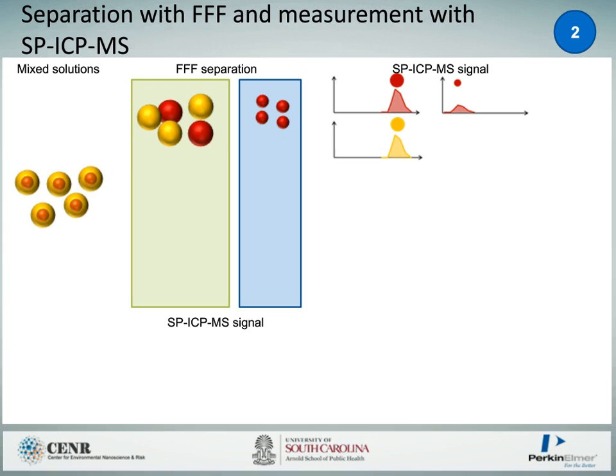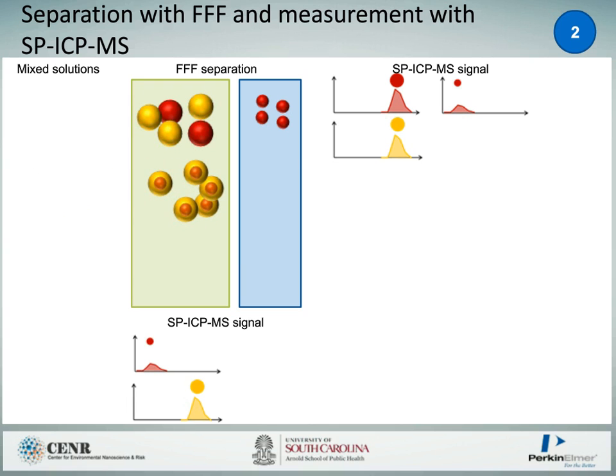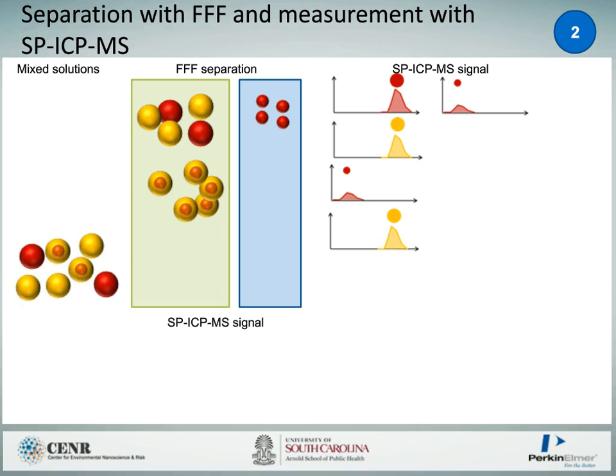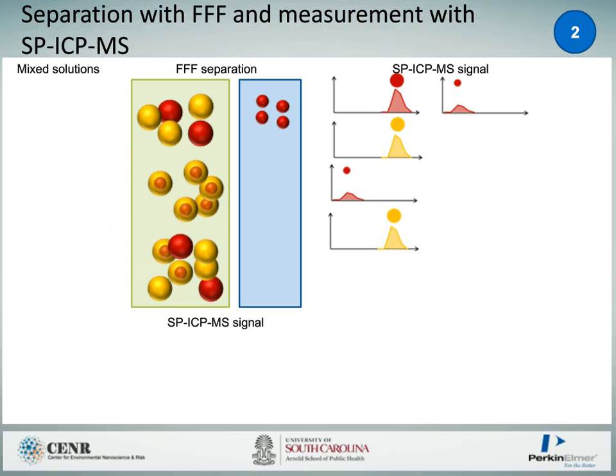So then if we looked at a bimetallic particle, say a core shell material, of a larger size, when those elute, they're only going to come out in the later fraction. But then when we measure with single-particle ICP-MS, we're going to see a much smaller size for the core and a large size for the shell. This is to do with the x cubed number of atoms per nanometer of particle as you go out in diameter. So then if we had a mixture of monometallic and bimetallic particles, these will all elute in the later fraction. And at this point, what we're going to end up with is two peaks coming in the gold signal, where we're having a small fraction from the core shell material and a large fraction from the monometallic material, and then we're going to see the silver peak also come out separately.